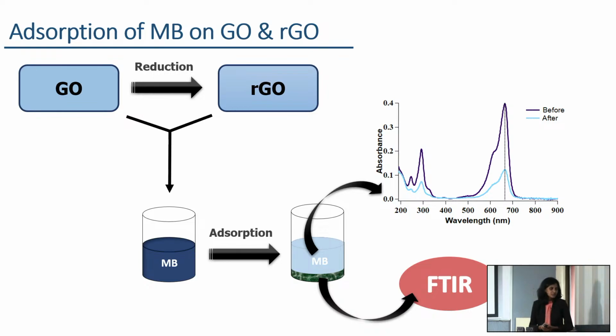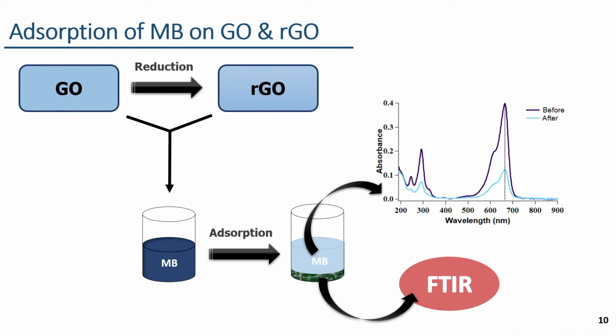Here, the methylene blue adsorption onto these GO and RGO was carried out by adding a known and excess amount of methylene blue into the suspensions of GO and RGO. After the adsorption process, the remaining amount of methylene blue in the supernatant was measured using the UV visible spectrophotometer, and the amount of MB adsorbed onto the GO and RGO was calculated based on these UV visible results.